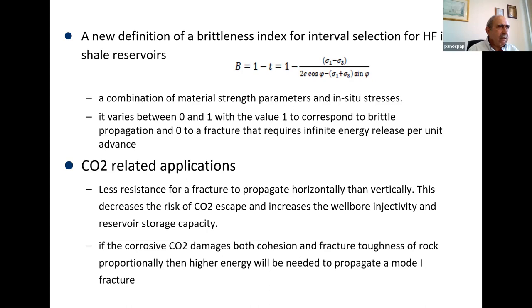Did you perform a sensitivity study on the dilation angle? How important is it in modified pressure and fracture width? Actually, as I say, the less dilatant material is between the elastic and dilatant. Lower dilation will get a slightly narrower fracture, but plasticity will still be there. So we need to separate dilation from plasticity, of course. We can have full plasticity with less dilatant material as for rock. As I say, what we know now is that for less dilation, we are between elasticity and the full dilation model.